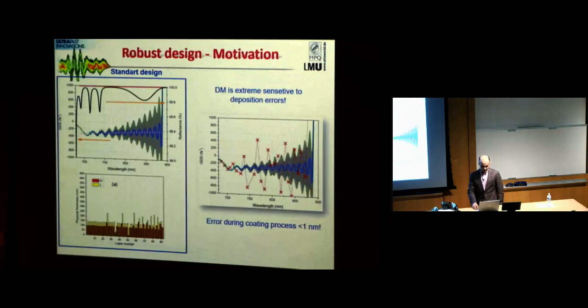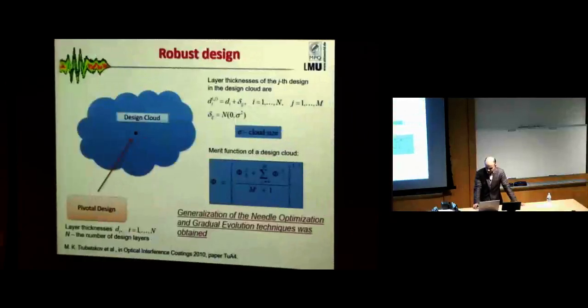One very important topic: I told you that when we produce a structure, it's very sensitive to deposition errors, and here is one example of this. We have a theoretical curve for GDD mirrors, shown in blue, and if we include deposition errors of plus or minus 1 nanometer, the curve can lie in the gray corridor, and it's shown by the red points here. We apply a very special design, which we call the robust design algorithm.